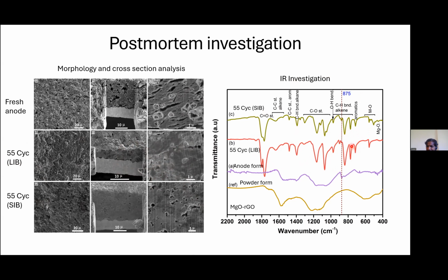There are several functional attachments after cycles. This is because of the electrolyte traces, because organic electrolyte traces and several things will come. And the main interest is how these magnesium oxide bonds fare, whether they are existing there or not. A slight perturbation, maybe, we observe in the case of lithium ion battery, but still the pillar structure remains, and that's good news. So good structures, and structures like this need to be synthesized in the laboratory to reach a breakthrough in energy research.